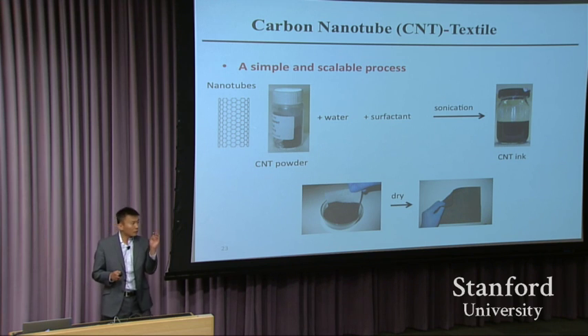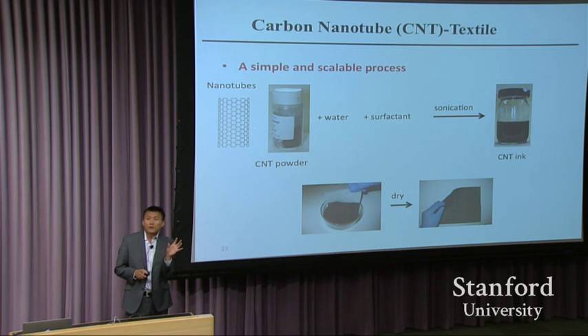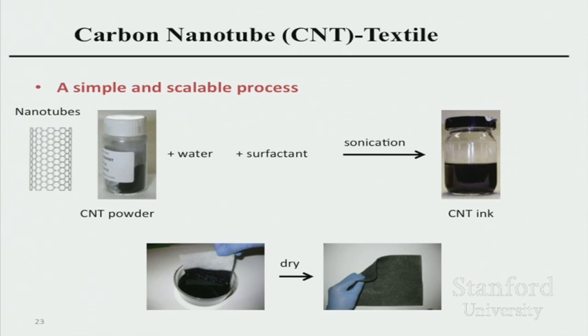So in order to make a good electrical interface with the microbes, we learned something from the past 20 years of development using, for example, carbon nanotubes. That's right here. It's very conducting, with a diameter of a couple nanometers. And you can buy it now as a powder, add water and surfactant, and disperse it into an ink of carbon nanotubes. And then you can put in a textile, the stuff you wear, get it from Walmart, right? When we did the experiment, students went to Walmart to get it and dip it into this carbon nanotube ink. This ink will just wet this textile. You take it out, you dry it.